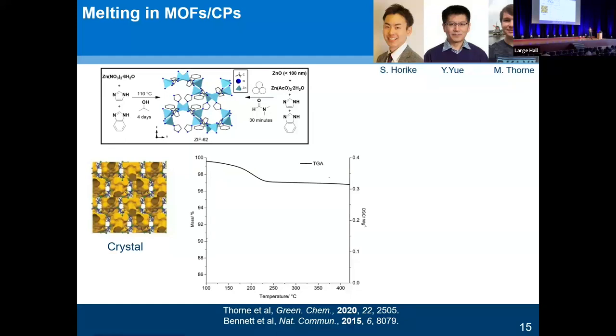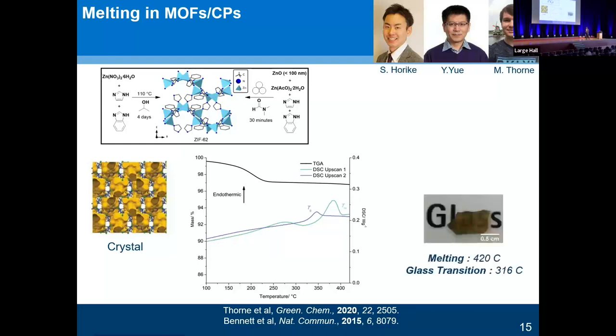The second reason, however, why this is just a poor assumption is because TGAs tell you nothing about phase transitions which are not accompanied by mass loss. No mass loss, TGA is going to be flat. It's the very definition. When we do a DSC, so when you look at the heat difference between your sample and a reference, you actually see a beautiful melting peak in a plateau. And upon reheating, this wonderful glass transition behavior that I talked about in one of the first few slides. So the material is not a white powder, it's not white microcrystalline anymore, but it's this beautiful glass.